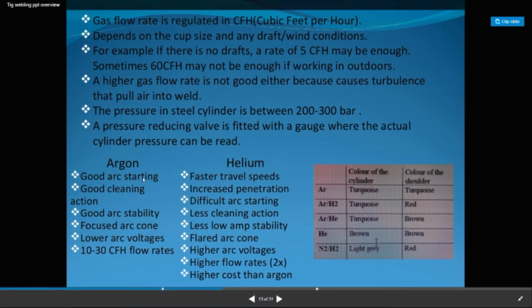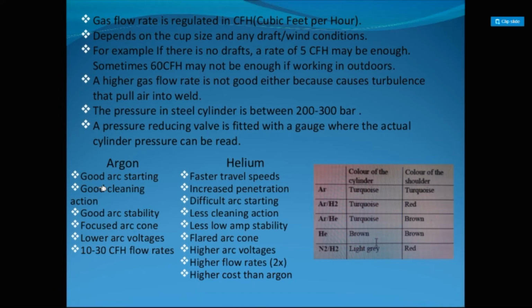Here you can find the different characteristics of argon and helium. Argon has good arc starting, good cleaning action, good arc stability, lower arc voltage, and 10 to 30 cfh flow rates, whereas helium has faster travel speeds, increased penetration, difficult arc starting, less cleaning action, less weld pool stability, a flared arc, higher arc voltage, and higher flow rates.